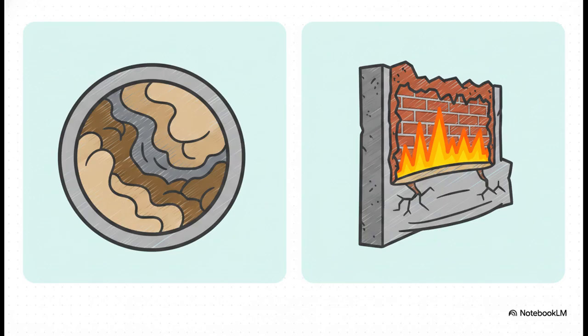It acts as a thermal insulator. It completely prevents the heat of the furnace from passing safely into the water. So, because that intense heat can't escape into the water, the metal boiler wall underneath the scale just overheats. It expands unevenly, then the brittle scale cracks, and suddenly, relatively cool water rushes right into that crack, hitting the superheated glowing iron plate. It instantly flashes into a massive volume of steam, creating a sudden, violent spike in pressure that can literally burst the boiler apart.